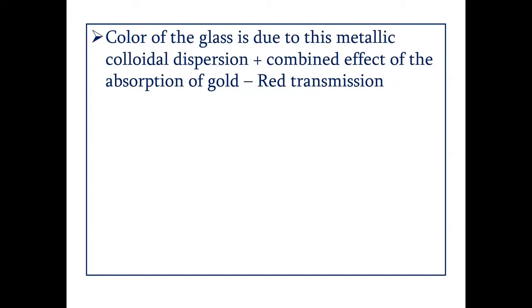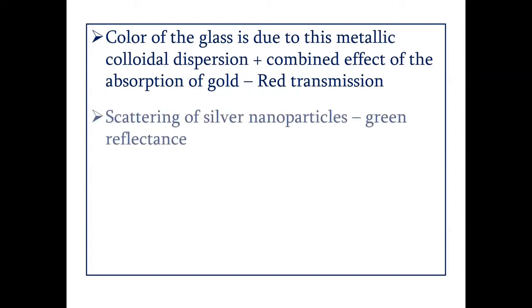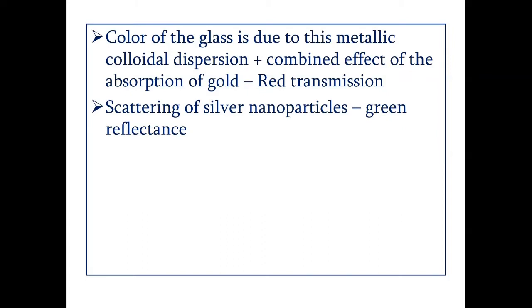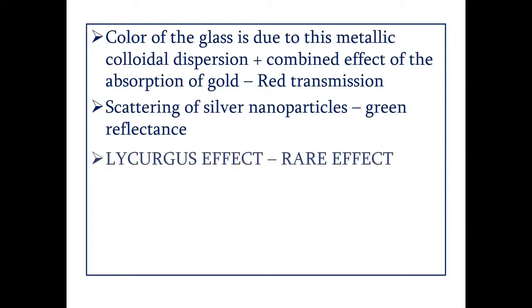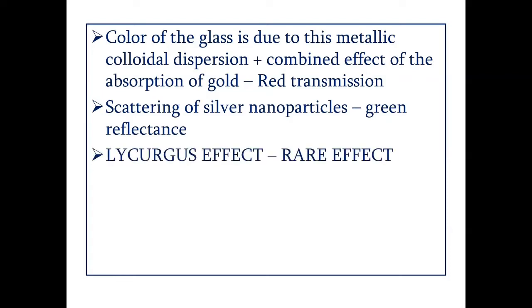And the color of the glass is due to the metallic colloidal dispersion and the combined effect of absorption of light by gold, which gives the red transmission, the red color when it is lit from the inside, and the green reflectance, which is the scattering by the silver nanoparticles when light falls on the cup, because of the reflected light. This effect we call the Lycurgus effect, and it is not unique to all glasses. It is a very, very rare effect which is exhibited in the Lycurgus cup.